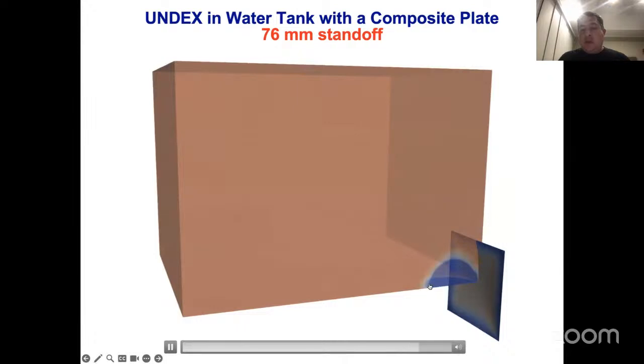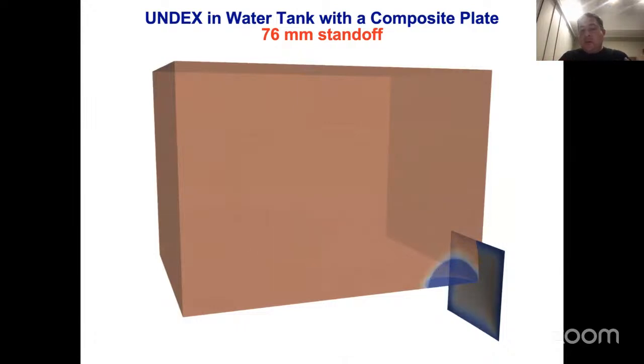And then you see a very slow growth of the explosive bubble, okay? And that explosive bubble continues to interact and deform the structure, right? And then the process continues because that bubble collapses and then it re-expands again. And so you have this very wide range of timescales that you need to track in the problem, right?